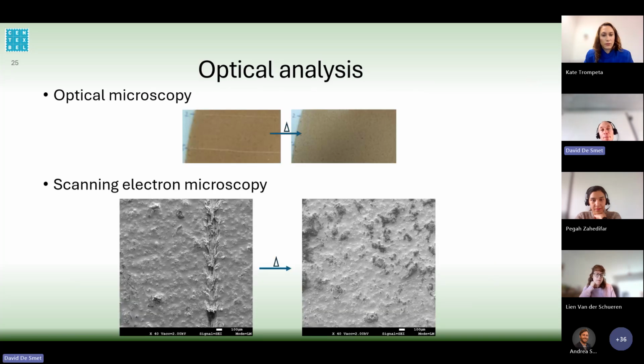Another way, as already mentioned, to assess the healing behavior is just by looking at it with the naked eye. So, for instance, with optical microscopy. And here you can see it clearly from the coating. This is one of the examples of the formulation that we have. At the left you can see the scratch we made, and then after just heating, in this case at 80 degrees, you can see that the scratch is gone for both scratches. So we made a scratch with 2 Newton and 5 Newton, and in both cases the scratch is gone.